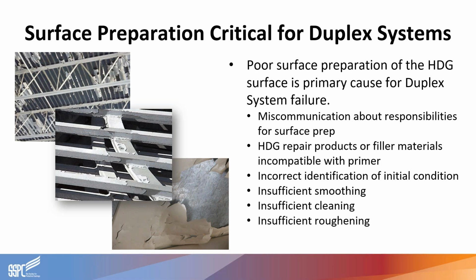And then beyond that, the painter may not be expecting that galvanized steel is what will be arriving at their shop. This becomes a problem because the standards for hot dip galvanizing allow minor surface conditions to be present. There's roughness, bumps, oxidation, high spots, or other areas where we can have excess zinc, which normally are acceptable because they do not impact the level of corrosion protection you can get with hot dip galvanizing when it's used as its own coating alone. However, these exact same surface conditions may negatively affect adhesion of a paint or powder coating applied over galvanizing.